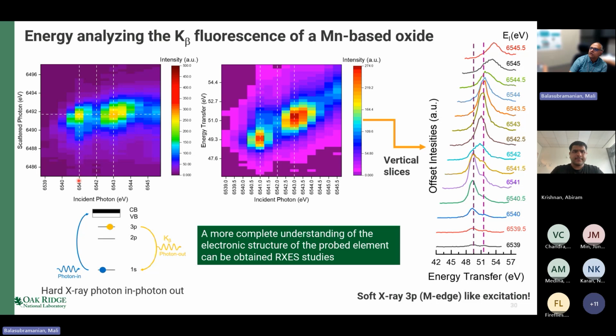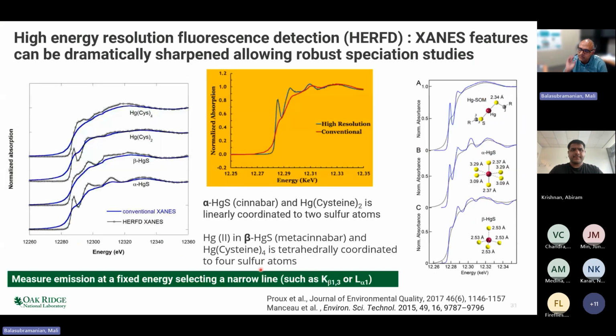And so you can do these cuts on these things. You can slice it. And one of the slices that is done here is to monitor the intensity at a given fixed incident energy, monitor the energy transfer. And you can see that this is an image-like spectra obtained at different incident energies corresponding to the pre-edge transition. So there's a lot of information in this spectra that one can mine and try to understand the d electronic levels. The other thing that can be done is an example that comes out of other fields.